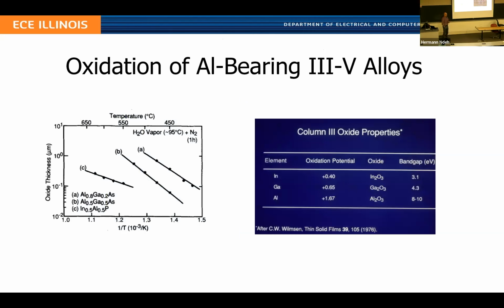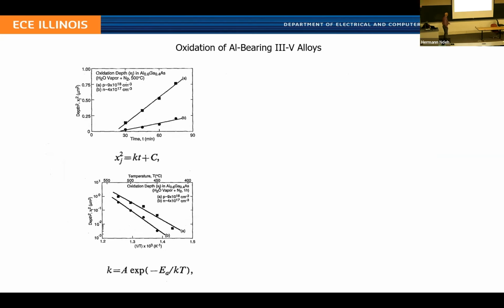In Illinois, we studied a lot of properties of this oxide when it was first discovered. Included in this was looking at various kinetics. We saw that high composition aluminum oxidized much faster than lower composition aluminum alloys, and AlGaAs oxidized a lot faster than indium aluminum phosphide. A lot of this you can pin back to the oxidation potential of the individual column 3 elements of the III-V. We also looked at a variety of other properties, including the fact that semiconductors of different doping types oxidize at different rates. Specifically, p-type doped samples oxidize much faster than n-type doped, and had a higher temperature sensitivity as well.